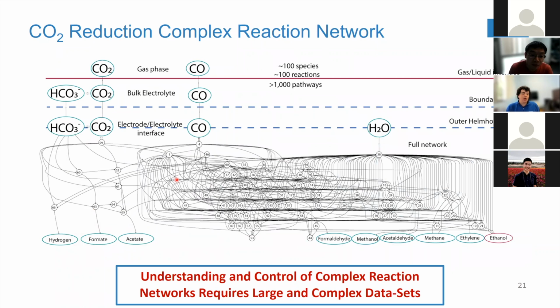The CO2 reduction mechanism is actually a very complex reaction network. You have more than 100 different species, more than 100 different reactions, and more than 1,000 different pathways to different products. The issue that we have in electrocatalysis is that we do 5, 6, 10 experiments, we change a little bit of some properties, and then suddenly we expect to understand the complexity of this network, and that is not the case.